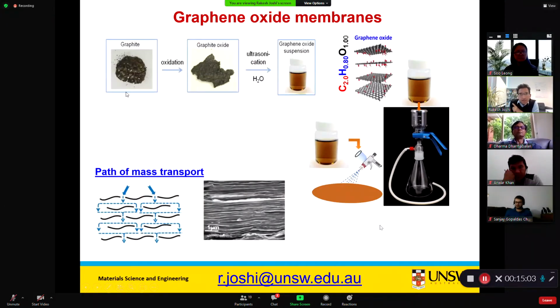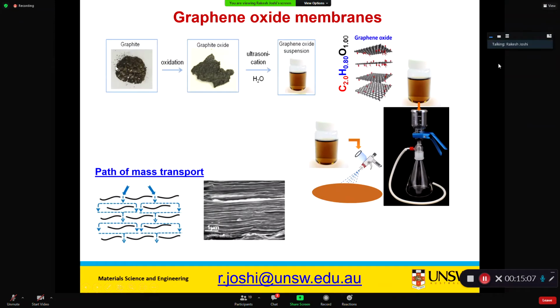And how we make it? This is one of the oldest methods, called Hummers' method. We use graphite, convert it into graphite oxide, then sonicate the flakes into monolayer flakes. Then the graphene oxide suspension typically looks like this. And once you have this suspension, you can make membranes, either by vacuum filtration, which is mostly what I do, or you can do spray coating also.